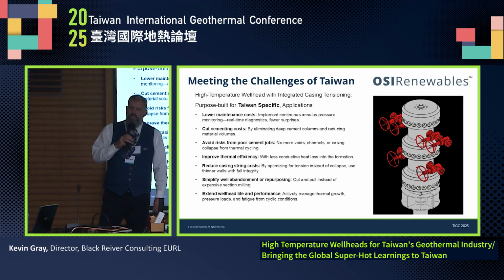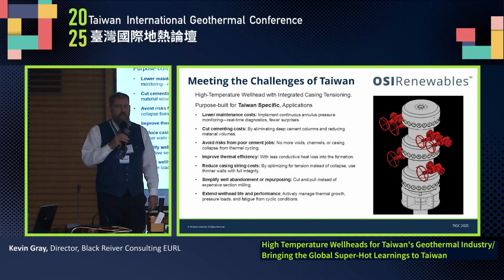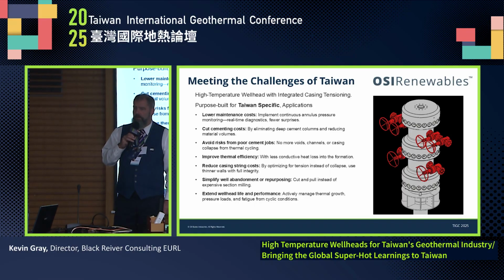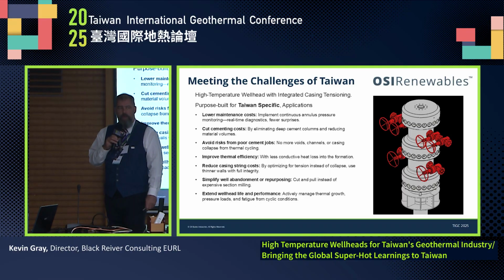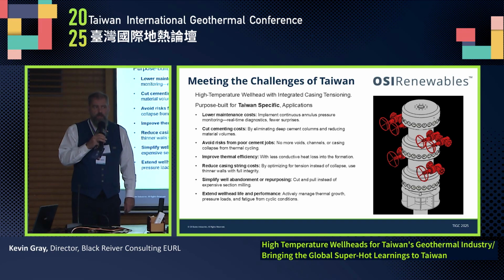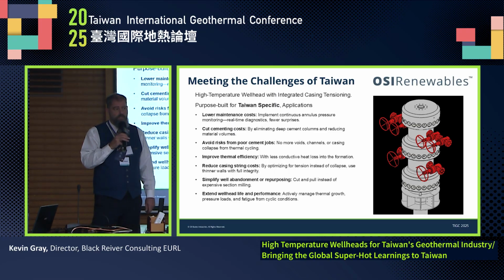Okay? But what's the other knock-on effect of running heavier wall casing? It's the fact that we have to have a bigger rig. If we've got a heavier casing string, we need a bigger rig to hoist that heavy casing string. And that might be a considerable impact on the drilling costs of that project. For example, if we have a small rig and we're running a lightweight casing, that rig's perfectly capable of drilling the well that we want. But if we suddenly specify a heavier wall thickness in our 9 5/8 casing string, for example, that rig may no longer have the hoisting capacity to actually run that casing string.